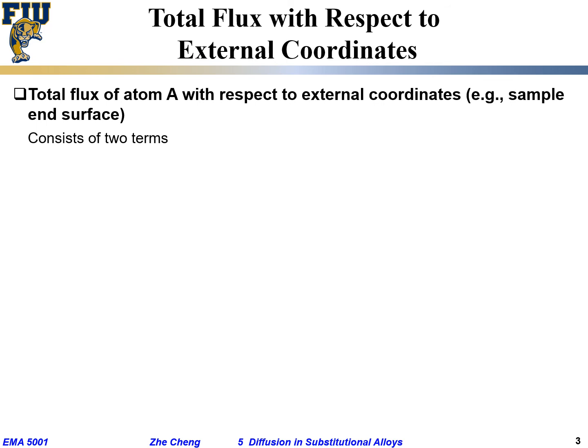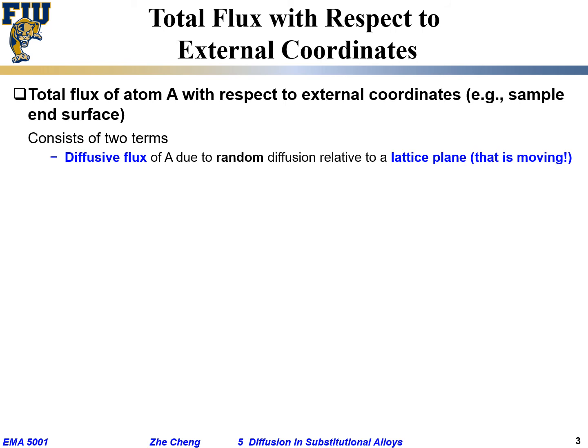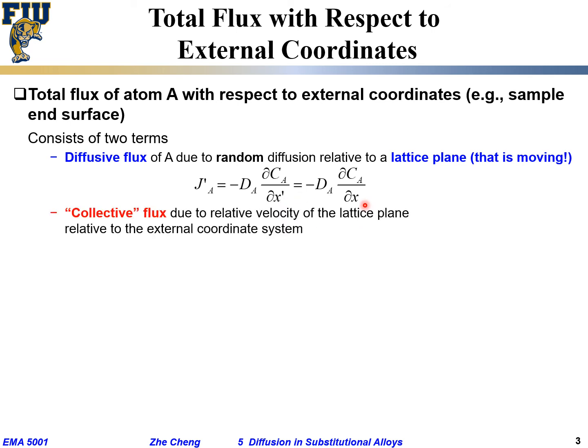Maybe you got confused. The atoms are moving. The total flux of A atoms will be two parts. The first part is the diffusive part, the random motion of A atoms. With respect to what? Relative to your chosen lattice plane, your moving reference point. The total flux, with respect to my chosen plane, is given by Fick's first law: dA, the intrinsic diffusion coefficient, and the concentration gradient with respect to the local moving coordinate, which is the same as the stagnant coordinate, plus another term.